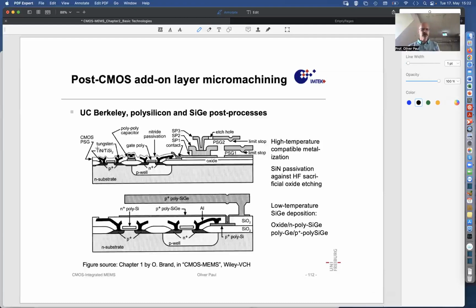What you see is again a full CMOS technology here, and then some area with micromachined structures. And what you should see here is silicon germanium. So those materials here are silicon germanium. And silicon germanium can be deposited actually at lower temperature than polysilicon. So you can do it even after completion of the CMOS process. However, note that some of the materials that are implemented here as metallizations are tungsten. Well, tungsten is known as a metal that can experience high temperatures. It's the one with the highest melting point. There's titanium nitride, titanium silicide. Those are also highly stable compounds. So you are not actually restricted so much in this process here with the silicon germanium.